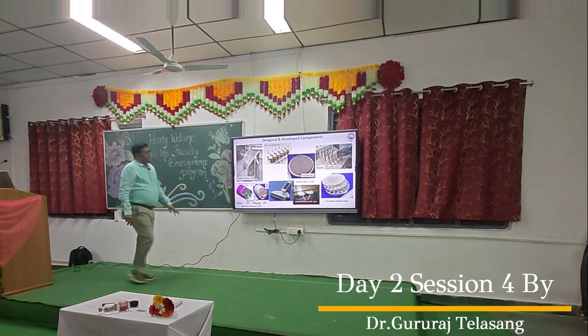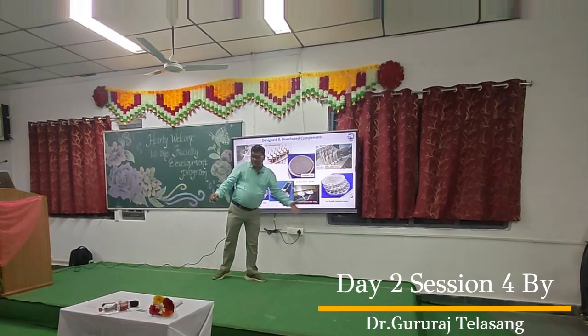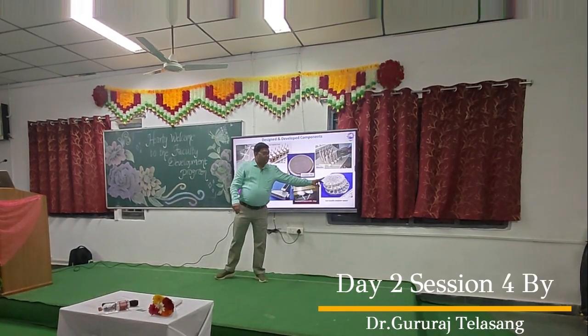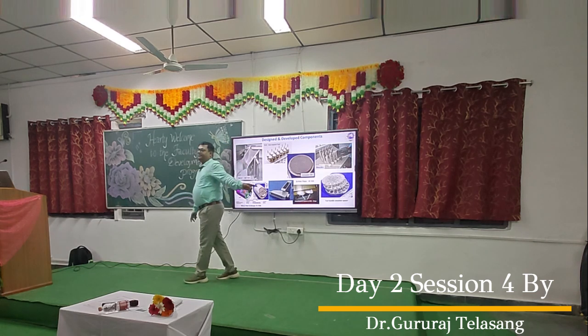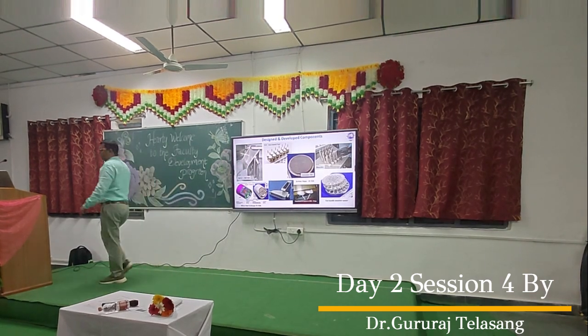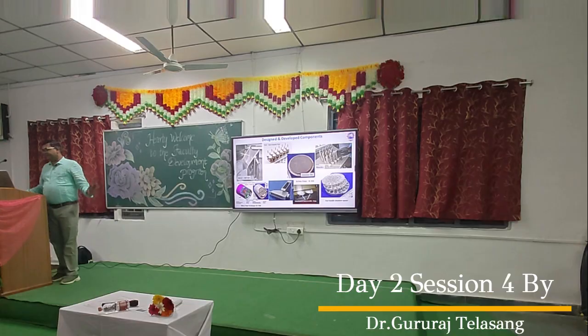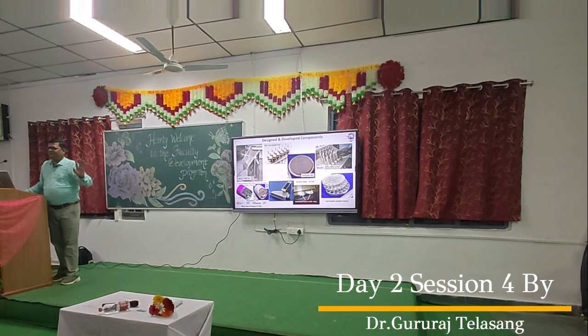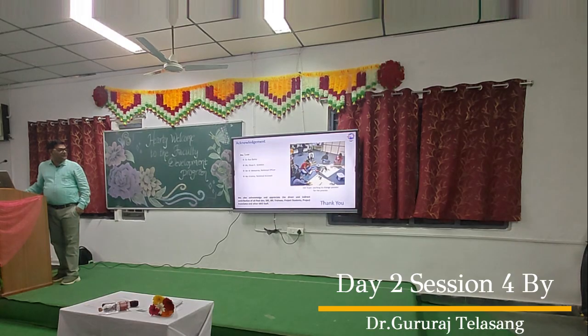This is used in a reduced pilot scale nuclear reactor, BARC. The entire project was held up because of that. This is a stainless steel part, very critical. Conventionally they were struggling. We just made 3 of them in 3 hours, and we sent them. They were surprised and they were saying, what? They were very happy. So those things we did.